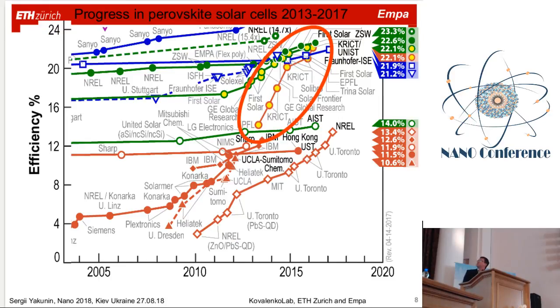Now this graph is the best illustration of why these perovskite materials are so important and why they took so much attention. Actually, what I heard is that nowadays this is the most cited material in the literature, because before it was graphene and two-dimensional materials, and nowadays it's perovskite. If you look, this is the starting point of the record for power conversion efficiency, and within just a couple of years it almost doubled, reaching now 22% and really competing with silicon solar cells, which are the main material now in the solar cell industry.